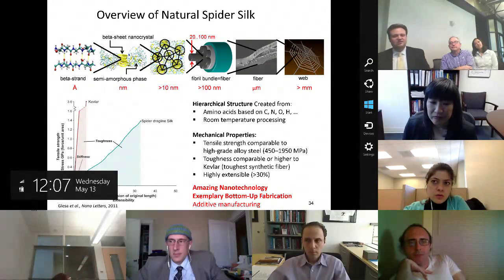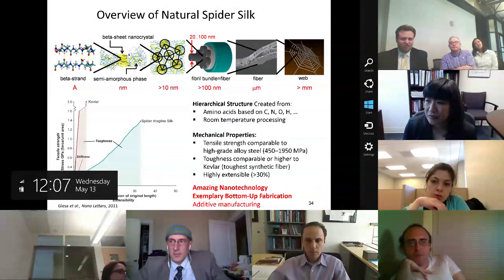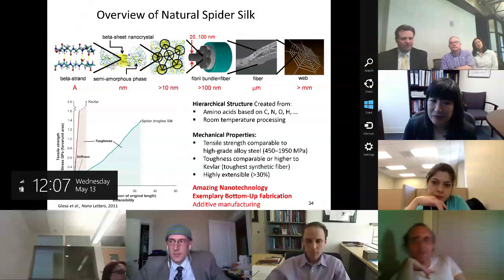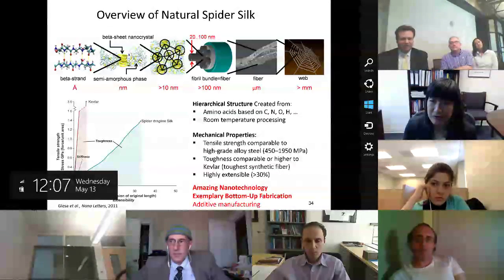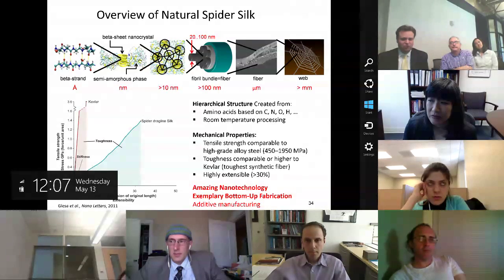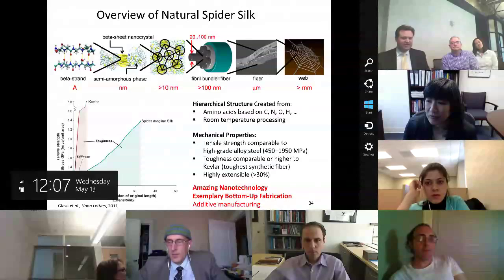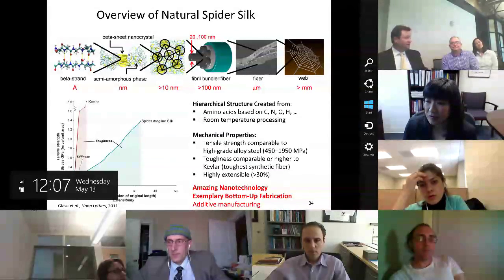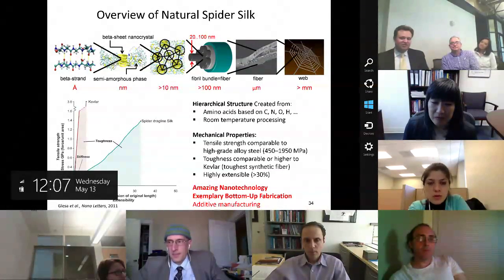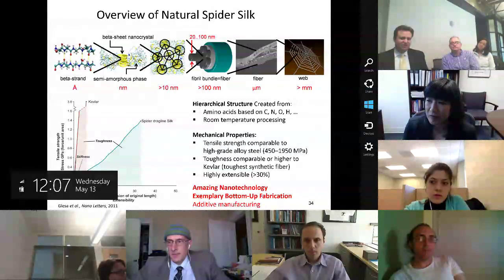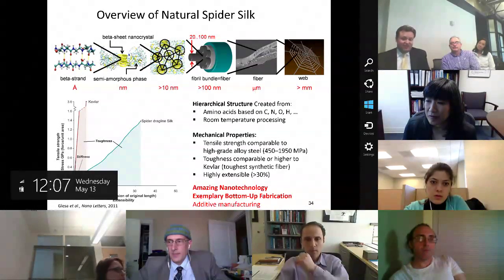So in other words, in silk, since we know that the microstructure, nanostructure, is composed primarily of two domains, hydrophilic and hydrophobic domains, which form certain secondary structures, which again, as you've seen from David's data, we understand quite reasonably well, this type of parameterization works out very well.